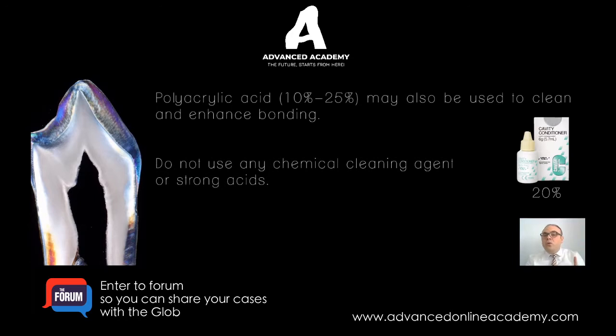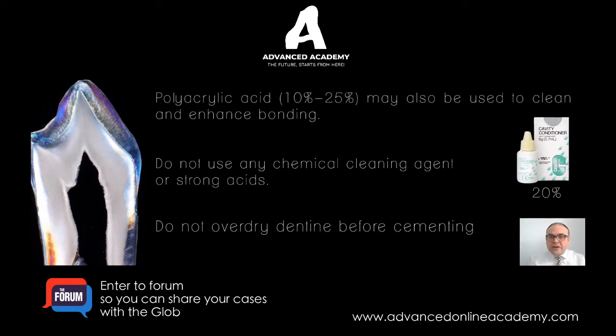You don't want to use strong chemical agents. Don't use phosphoric acid. You will demineralize the dentin and get rid of the minerals in the dentin. That is very important for the bond to the tooth structure. And never over dry dentin. This is the basic principle of adhesion. You never want to over dry your dentin before the cementation process.